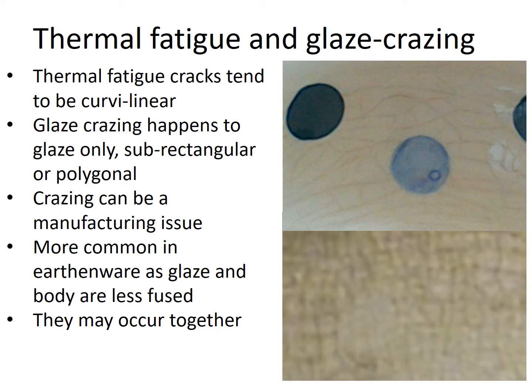So, how does heat actually break ceramics? Ceramics are rigid. Because ceramics conduct heat poorly, heating and cooling will cause different parts of a pot to try to expand or contract at different rates to other parts. If a pot is heated suddenly from room temperature, its surface attains a very high temperature in a very short period of time, while its core remains cooler. The surface expands while the core does not. This produces compression at the surface and tension in the core. The core is literally pulled by the expanding surface.